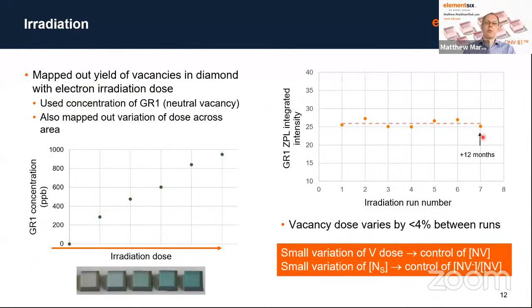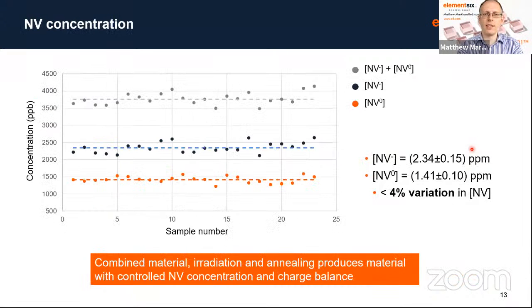Obviously, you need NV defects. So how do you produce those? We produce them via electron irradiation, because it's a very nice way of generating spin defects, or NV defects, in diamond without generating too many other defects. Initially we mapped out the irradiation dose versus the amount of GR1, which is the neutral vacancy, in witness samples. We then applied that to our diamond, and this plot shows the number of irradiation runs over a 12-month period, again showing consistent control. So we've got nice material with consistent nitrogen, and a nice process where we can irradiate it. Applying that to the diamonds, we see here a plot of multiple samples showing consistent NV concentrations with less than 4% variation. So we have this very nice material.